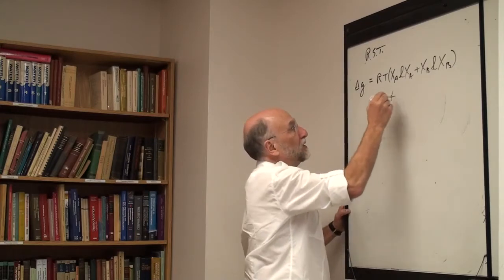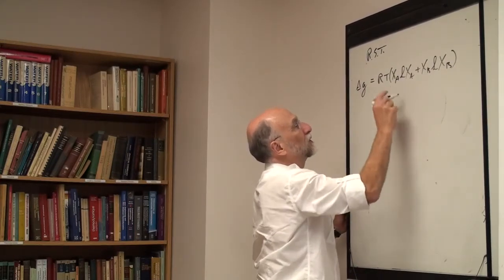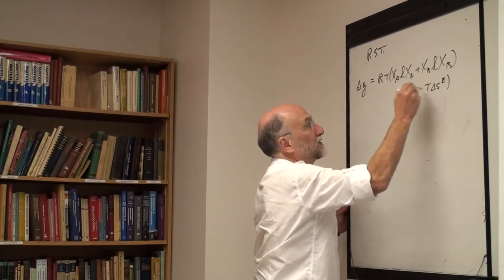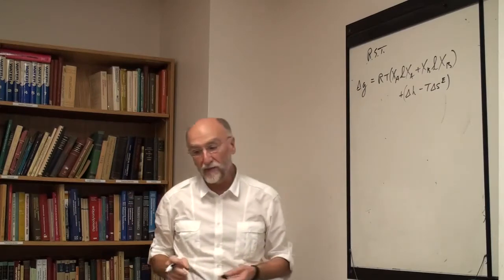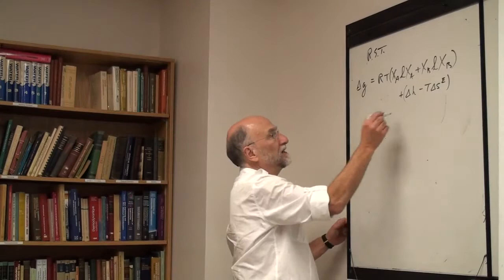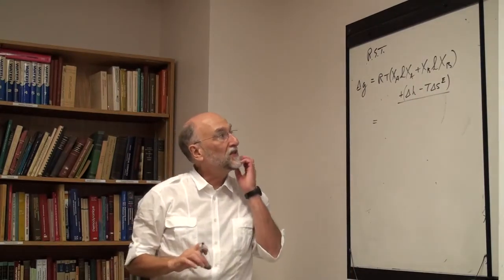And the GXS term would be the heat of mixing minus T times the excess entropy of mixing, those two terms together being the excess Gibbs energy. Okay, in regular solution theory, we used a quadratic expression for the heat and the entropy of mixing.